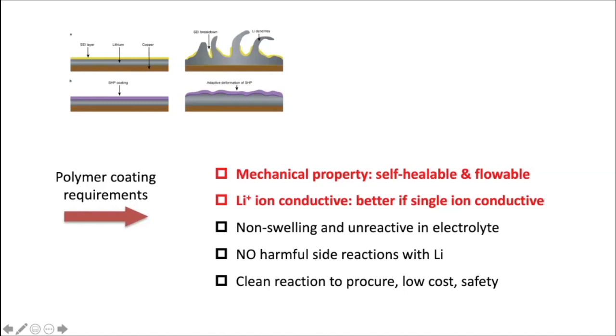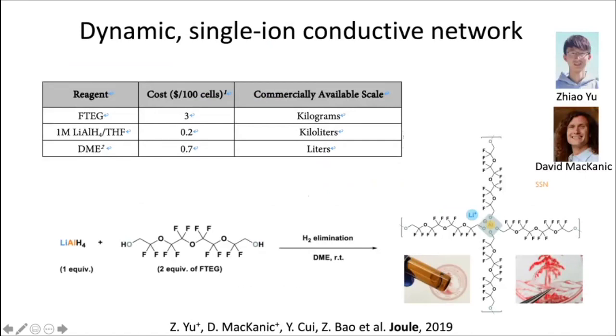And then we need to have a good lithium ion conductivity, and even better if single ion conductive. But at the same time, in order to prevent the reaction from the reactive electrolyte solvent, we will want this layer of polymer to be non-swelling by the electrolyte solvent, yet still able to transport ions through these single ion conductive channels. So that sounds like conflicting requirements, but indeed we were able to come up with the appropriate design of the system.